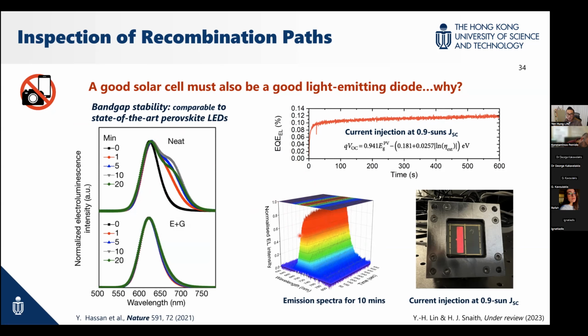Normally, we will see phase segregation and also halide segregation, especially halide segregation. So this is a state-of-the-art perovskite light-emitting diode using quantum dots. If it doesn't have any treatment, it just has this kind of segregation right away. This is work published by my colleague 3 years back. The state-of-the-art perovskite using quantum dots, quantum-size material, is well preserved to last for 10 minutes